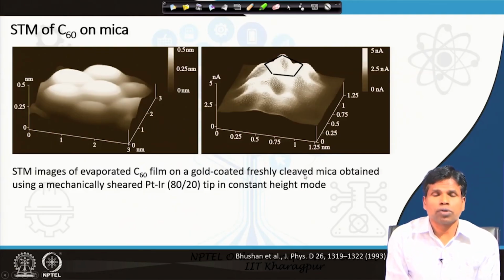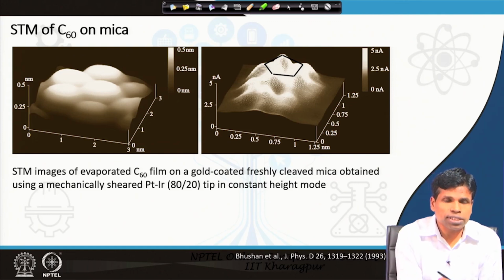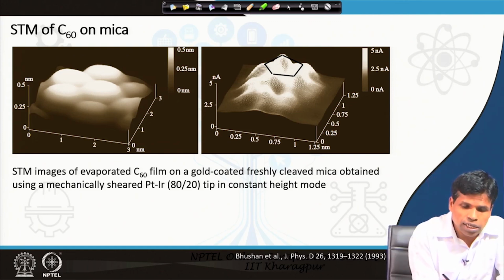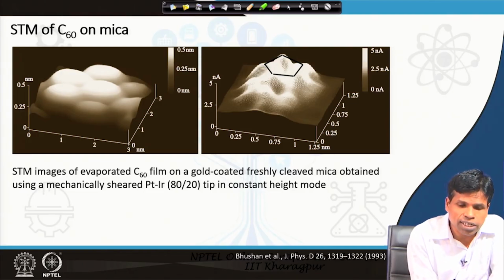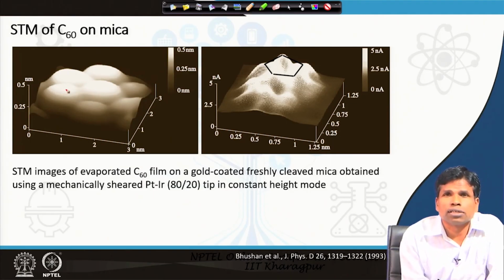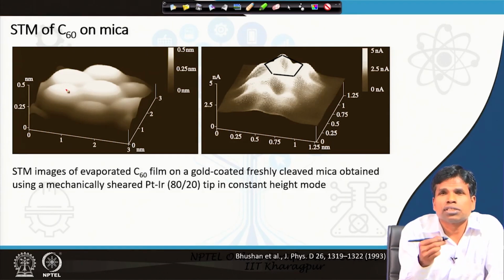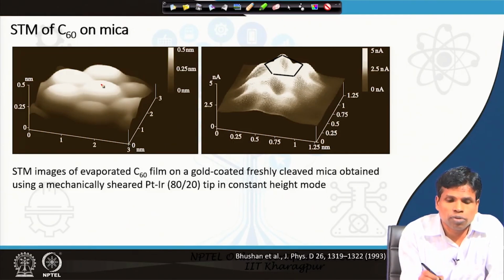Here is an example of C60 fullerene on mica. On the left side, what you see is a constant height mode measurement. In the constant height mode, at the top of this fullerene molecule, which is a sphere type of molecule, you see very bright features. Bright means it is measuring a high current, more tunneling current, and therefore you see more brightness.